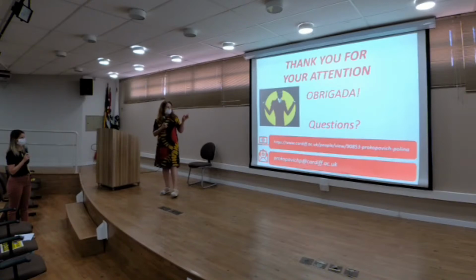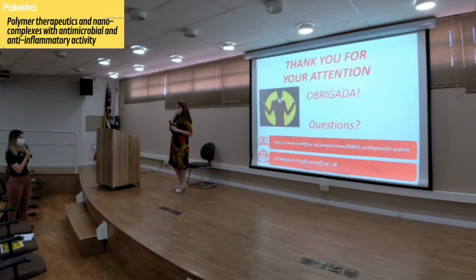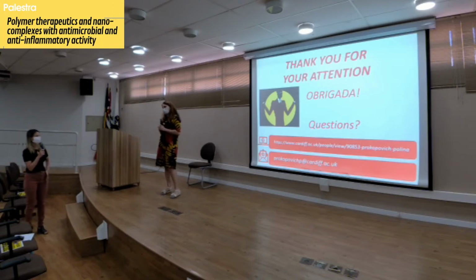We did that. This is the last study I showed you on dexamethasone, but there was another study by my PhD student, who finished two years ago. We published that. We functionalized titanium implants, and we made layer-by-layer deposition on top of the implant itself without nanoparticles. Does it interfere with the surface of the implant, like its roughness? It's very insignificant because the implant is very rough, on purpose. The coating which we create is on a sub-micron level, so it's much smaller compared to the roughness of the implant itself. It does not really change the roughness of the implant.